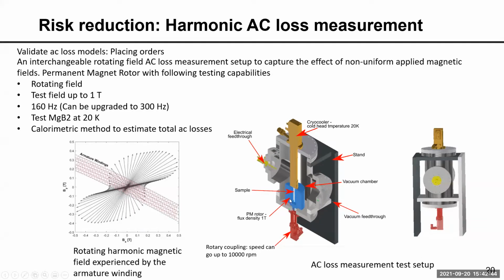So we need to simulate such a field inside this chamber to see what the losses on the winding are. For a start, we are trying to produce a pure sinusoidal rotating field and measure the losses on the sample. Here we have a permanent magnet attached through a vacuum coupler, and we can rotate this coupler up to 9,000 RPM. That translates to 160 Hertz because it is a two-pole permanent magnet rotor. Then we place the sample inside it to measure the losses on the sample.